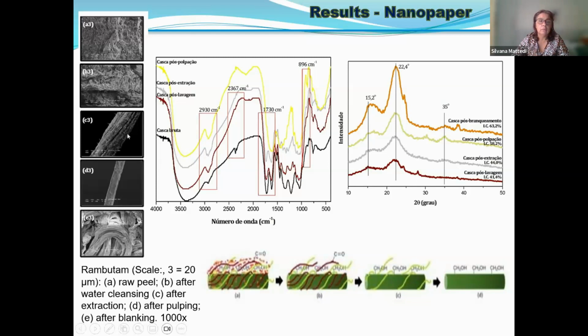After we extract with ethanol most of the extractives of the fiber, and after we pulped and bleached the fiber, the liquor was used for producing lignin, which is not shown here because it was not the focus, from the liquor obtained here from rambutan. And you can see the characteristic bands of the characteristic compounds of cellulose, and you can see that the treatment leads to a higher crystallinity.